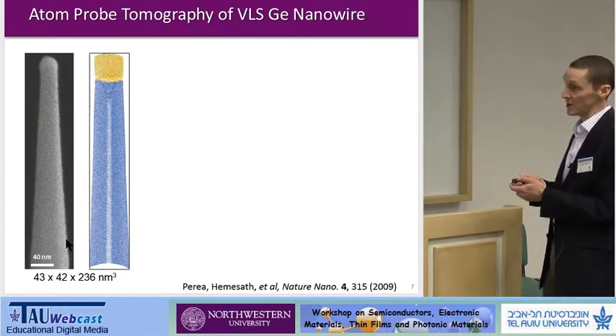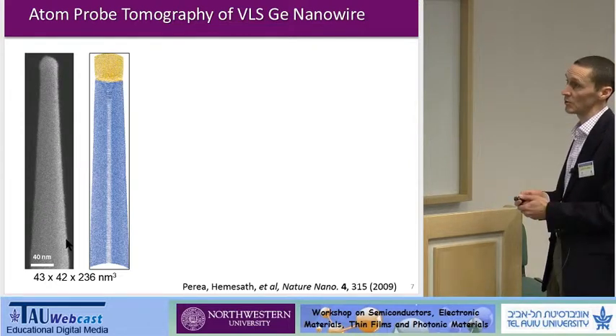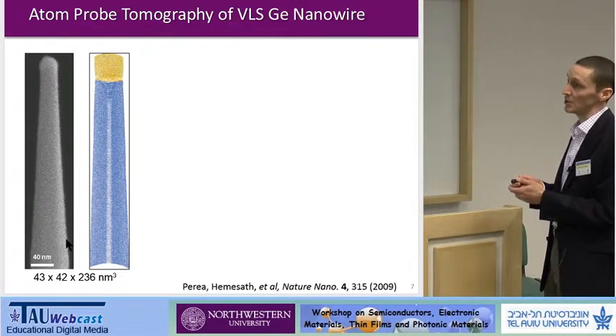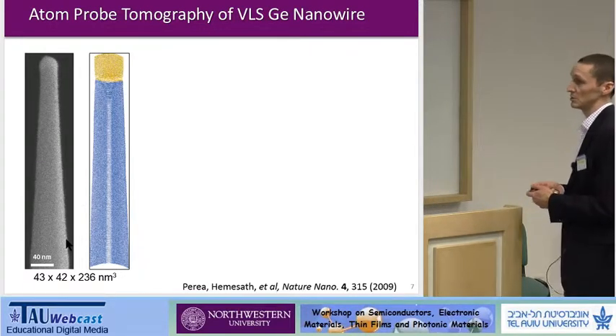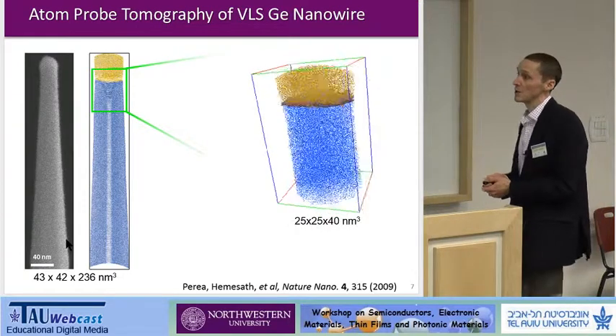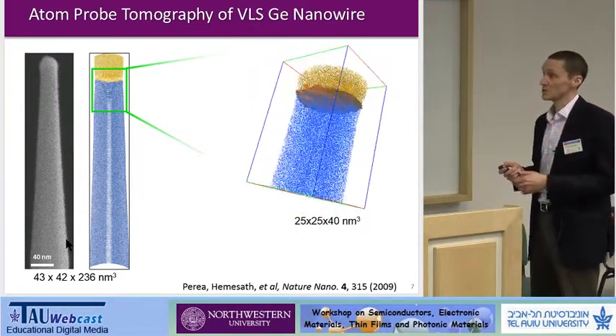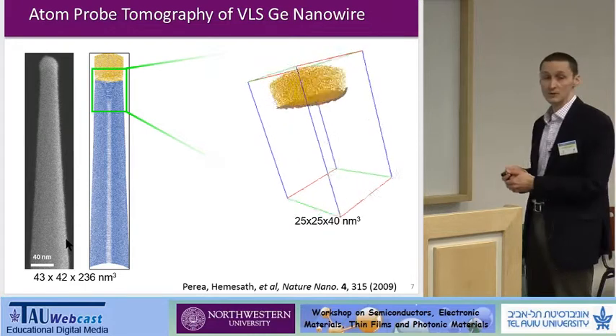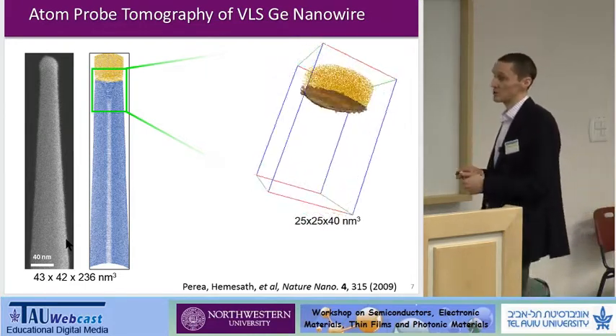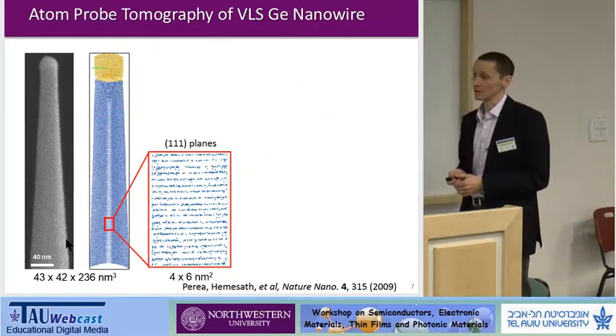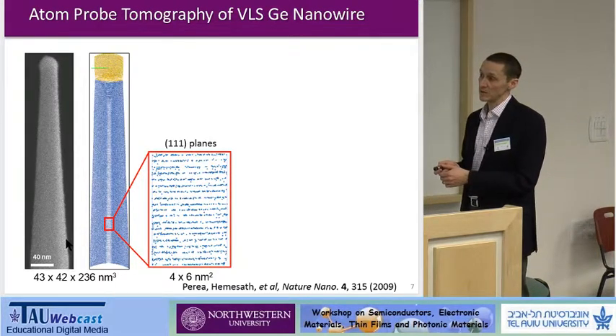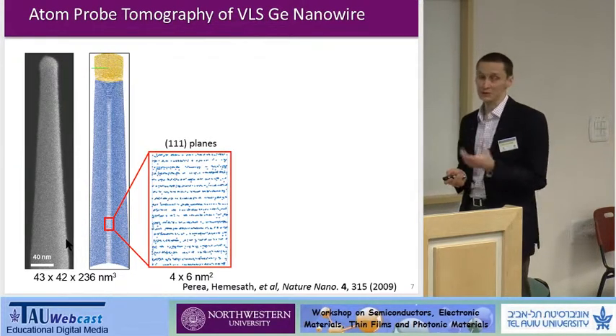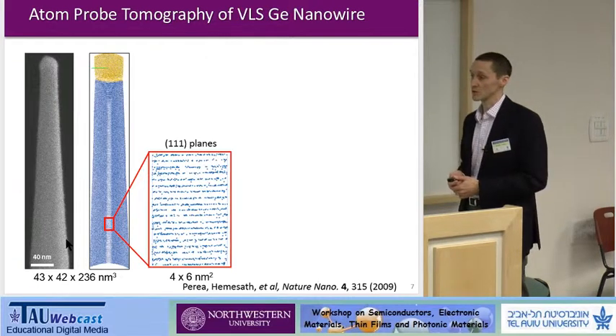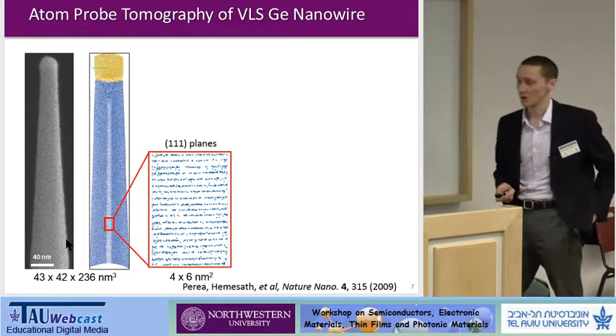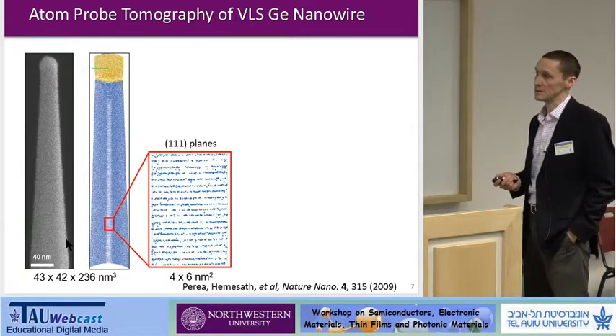So on the left is an SEM image of a slightly tapered nanowire. And if you look at it in the atom probe cross-section, you can see that there's this gold catalyst at the top. And in this case, these are blue-colored germanium atoms. Okay. So looking at this in 3 dimensions, it highlights that we can image buried interfaces. That's one of the powerful aspects of the technique. And we can do so with atomic resolution, which you can see by examining these 111 planes that occur in the center of the reconstruction. So this is a nice internal calibration as well for the technique.